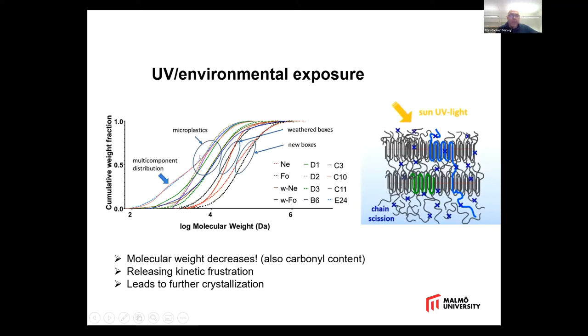And as it sits out there longer, and these are the materials that have been gathered from the Caribbean, the molecular weight goes down. So one thinks of the process as sunlight causing a more or less random scission of polymer chains in this material.